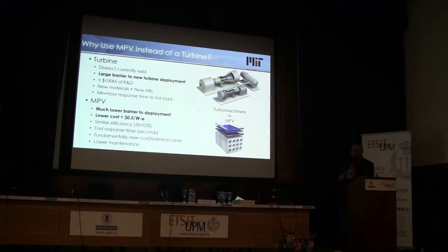So the new turbine would be very different than anything that exists today, in the sense that it'd be a closed cycle, Brayton cycle, would use an inert gas as the working fluid. You've also got new materials and new heat exchangers you've got to make. So now you've got compressed gas coming out of a compressor that now needs to be heated up to 1500 degrees C. So unlike how it works inside the turbo machinery itself and the expander, where you can have extreme non-equilibrium between the metals that are used for construction and the fluids that are flowing past them, the fluids can be much hotter, 600, 700, 800 degrees hotter than the actual metal gets. You cannot do that with a heat exchanger. You need the heat exchanger to get as hot as the fluid itself. So you can't think about using the same material. So this requires the invention of new heat exchangers. And last of all, there's this response time.